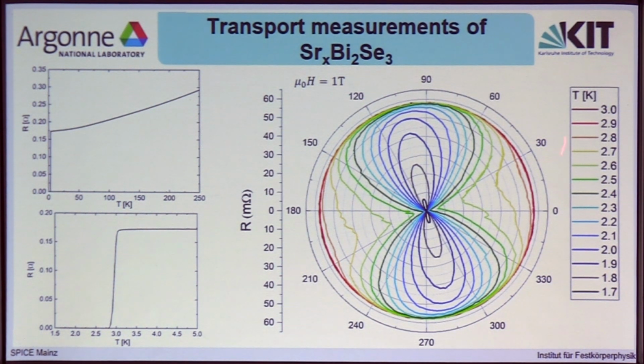color-coded maps here. So the red curves are for higher temperatures, and you can clearly see that as long as the temperature is so high that we are above the superconducting transition, the sample is normal and there is no anisotropy of the resistance. However, once we start going into the superconducting state, there are regions for the field where the sample is still normal, whereas there are other regions where for that temperature the sample is already superconducting, and this shows this clear twofold anisotropy.